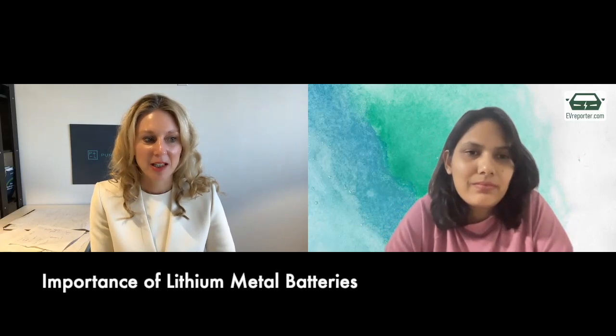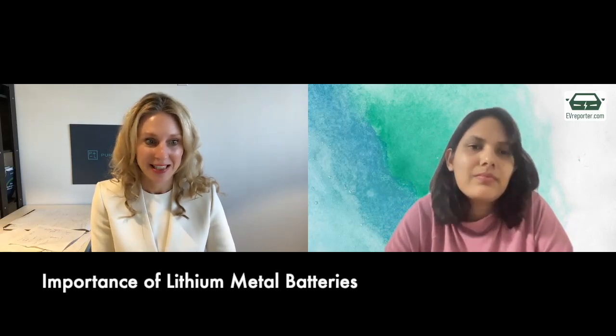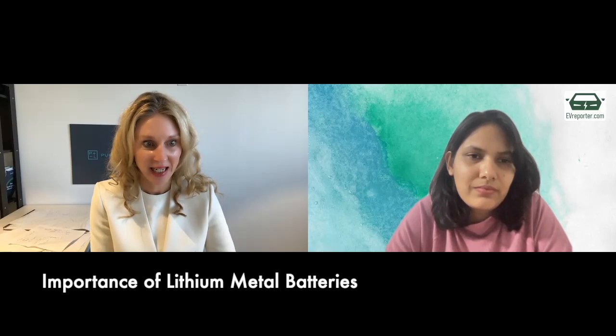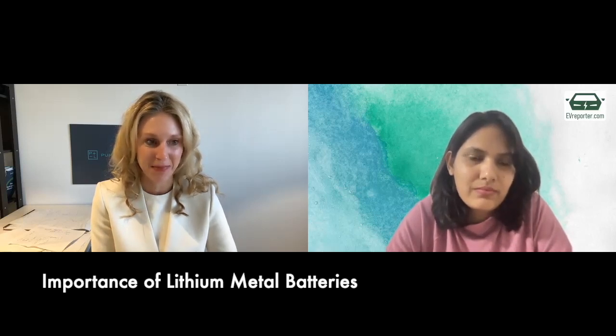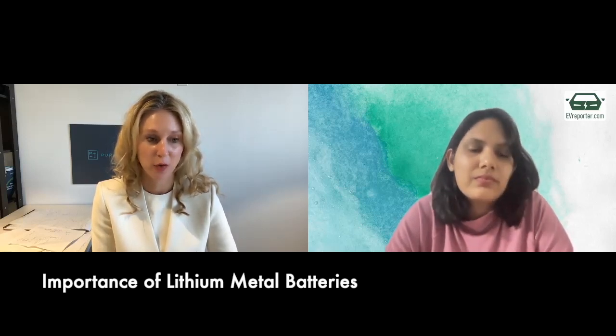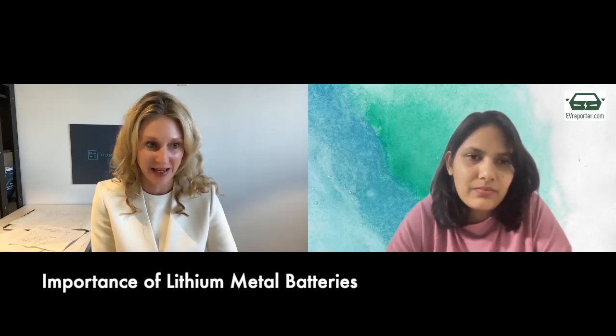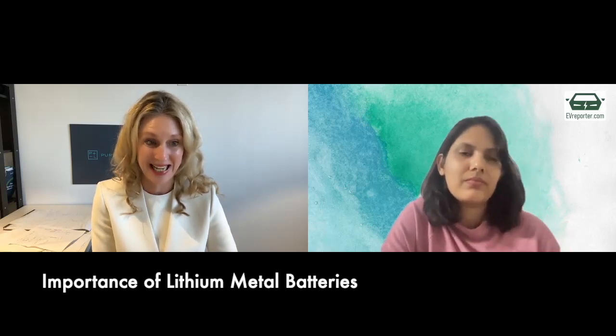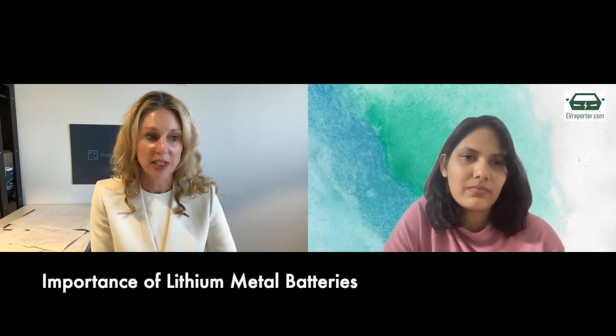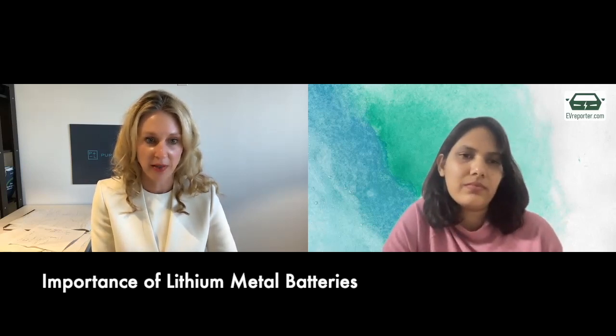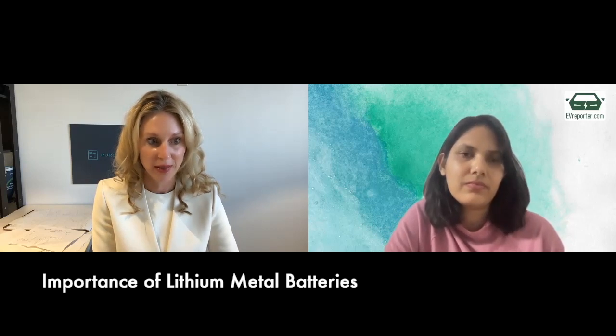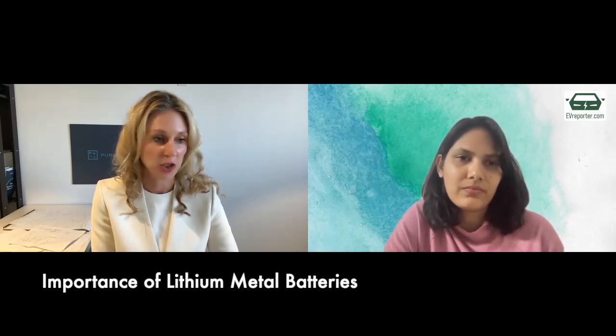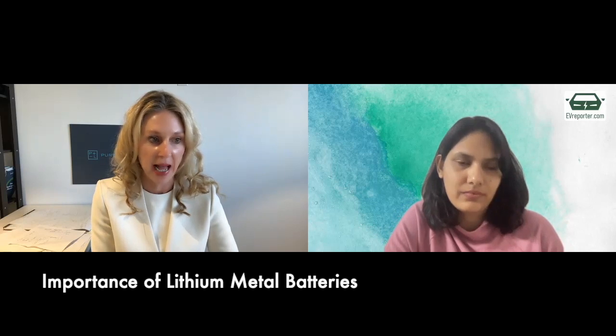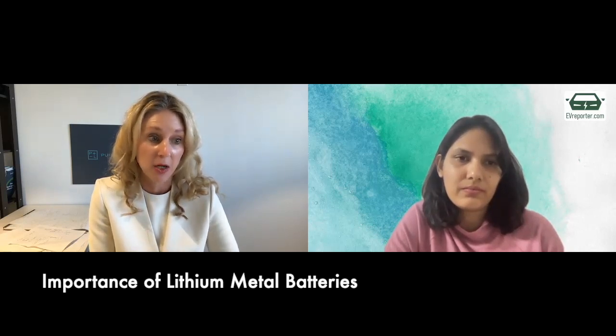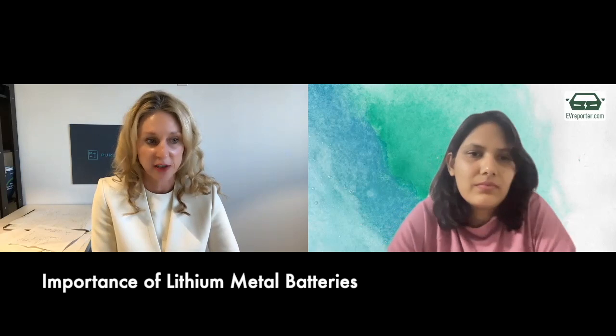Wow, thank you for the question. Lithium metal is really the holy grail of batteries. It has the highest energy density. It has 3,860 milliamp hours per gram, compared to the graphite anode in lithium ion today that has about 386. That's 10 times more. So using lithium metal, a thin, pure lithium metal electrode with the correct cathode can increase energy density by arguably 10 times. Realistically, on a cell level, at least 4 times.